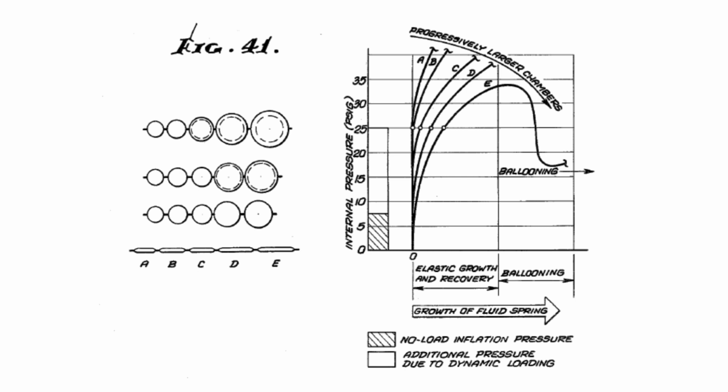At very high pressures, the largest chambers can be forced to stress levels which exceed the elastic limit of the material. This is indicated as ballooning in the figure and can result in loss of pressure and/or rupture of the material. As the curves indicate, however, a margin of safety is designed and built into the insoles so that the maximum expected working pressure is well below those pressures which would cause the tubes to approach their elastic limits. The margin of safety is more than sufficient to guard against such factors as excessive heat in the shoes, high-altitude effects, etc. The large volume increase in the system as it approaches the ballooning condition creates a highly effective self-stabilization characteristic. By this method, excessively high fluid pressures resulting from service, heat, altitude, etc. are self-correcting so as to enhance the overall service life of the product.